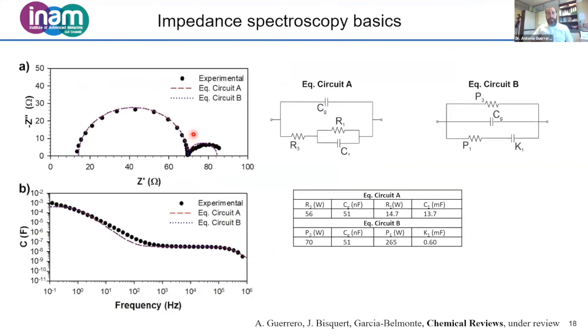Okay, so as I mentioned, there is some ambiguity with the equivalent circuits, and we need to use a well-validated equivalent circuit. And there is a reason why one needs to be well aware of the literature. So here I show as solid points the data points that we measure by impedance spectroscopy, and the lines are the fitting curves using this equivalent circuit A and this equivalent circuit B. Mathematically, both of them fit reasonably well the experimental data, except for these data points at low frequency. But for now, let's forget about this. As I mentioned, we can use the complex impedance plot, we can use the capacitance frequency plot, and in both cases, the fitting is relatively good.